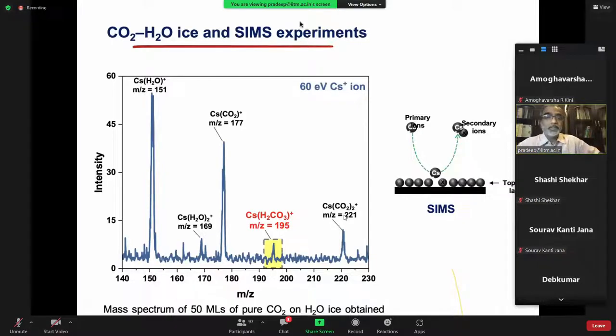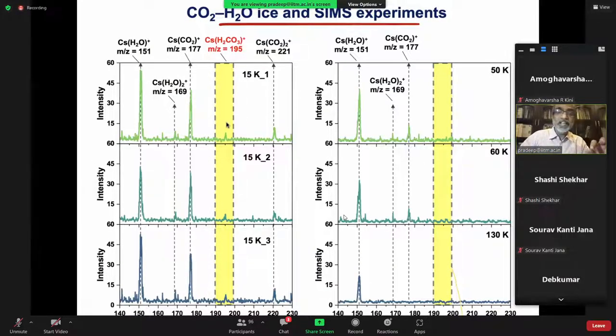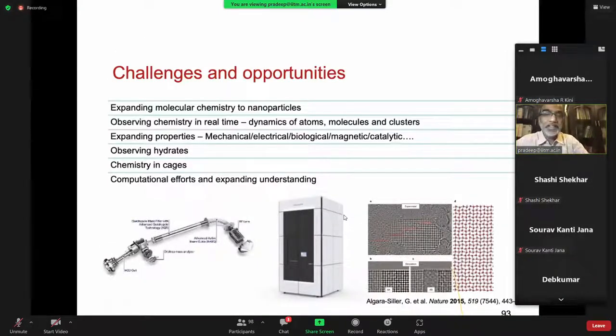But something very interesting happens. So if you put CO2 and H2O and come in with cesium ions at low energy, 60 eV, this can pick up water from the surface. This is known. Two water can pick up CO2 from the surface. It's a mixture. What is surprising is that you can pick up this carbonic acid from the surface only at such low temperatures. And here is 15 Kelvin. You can see this. But you go to higher temperatures, 50 Kelvin, 60 Kelvin, you don't see it at all. So very interesting new aspects are coming in atomically precise clusters and gas hydrates.